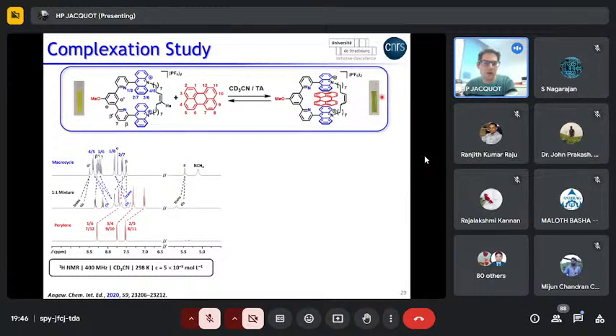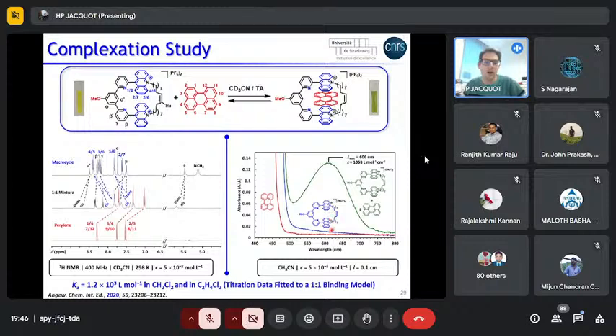This greenish color is the result of the appearance of a charge transfer band at 600 nanometers. So one more time, we have a partial electron transfer from the donor, here perylene, to the acridinium cores. Thanks to UV-visible titration, so following this charge transfer band, we were able to estimate a binding constant of 1200 molar minus 1 in DCM, which is a huge gain in comparison to the previous systems. So we were right to form the macrocycle. It does prevent the dimer formation.